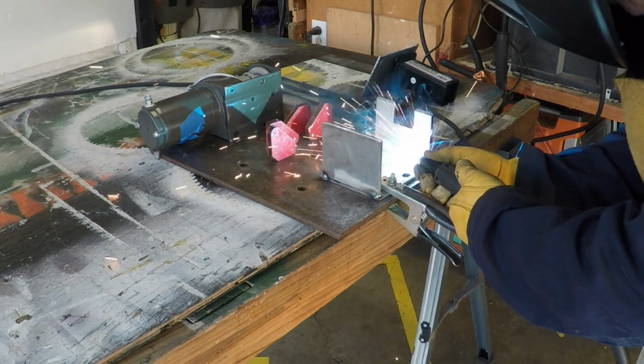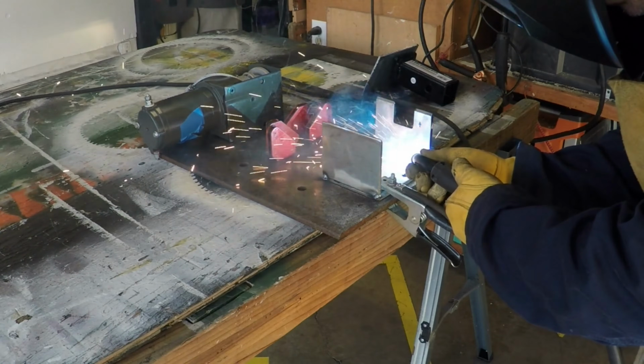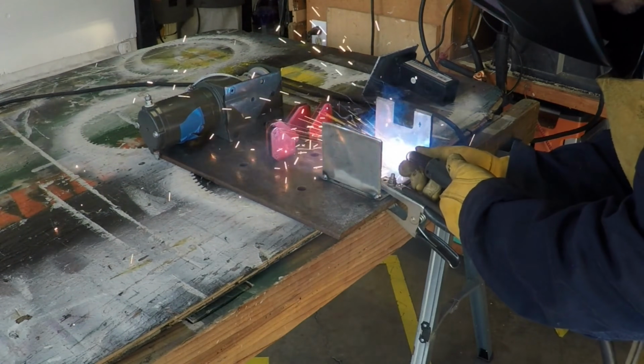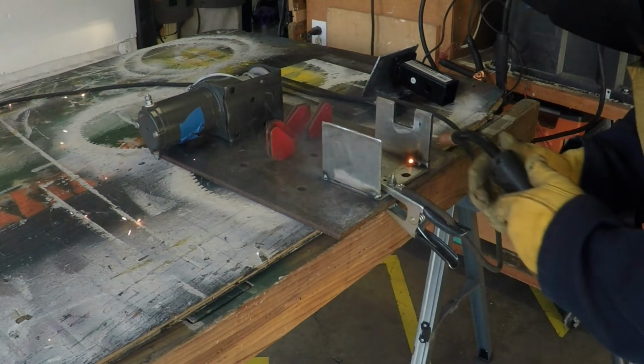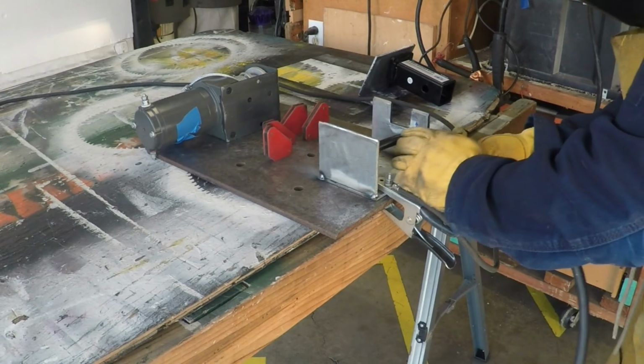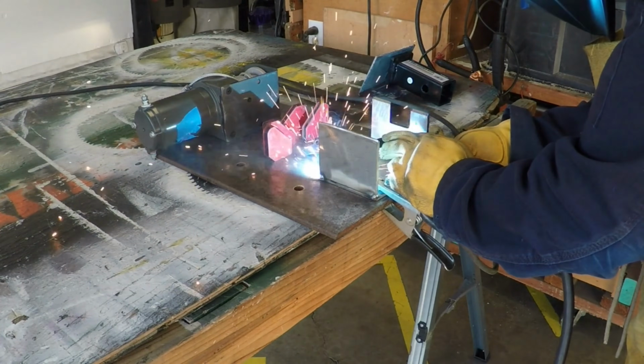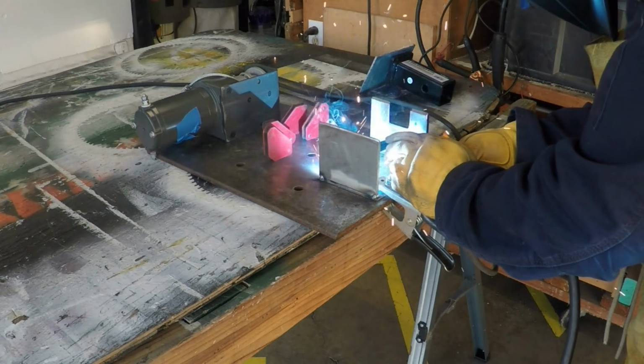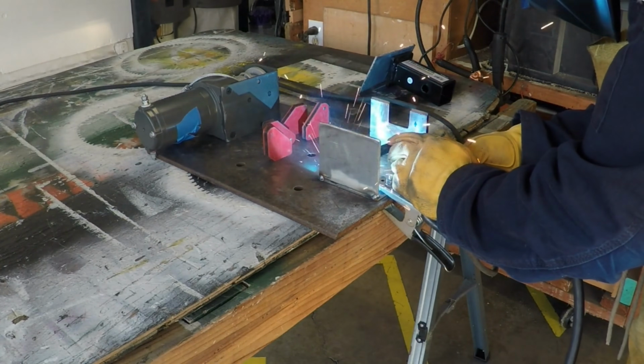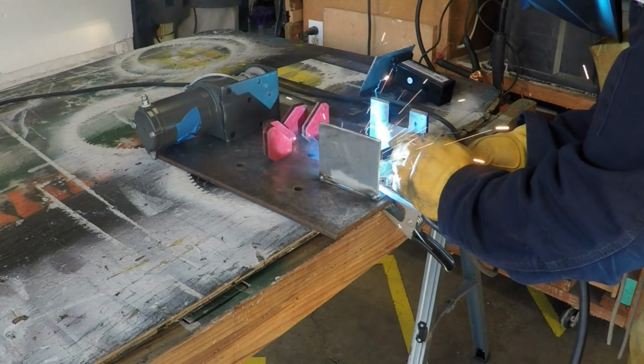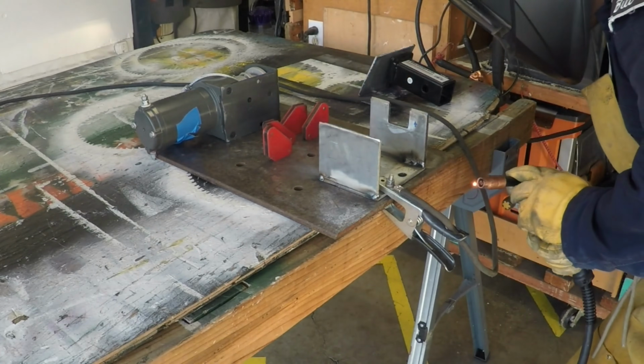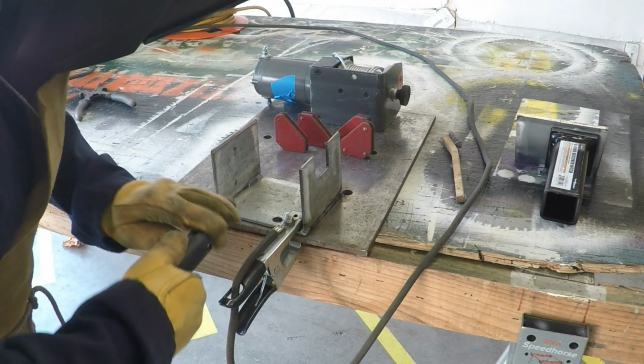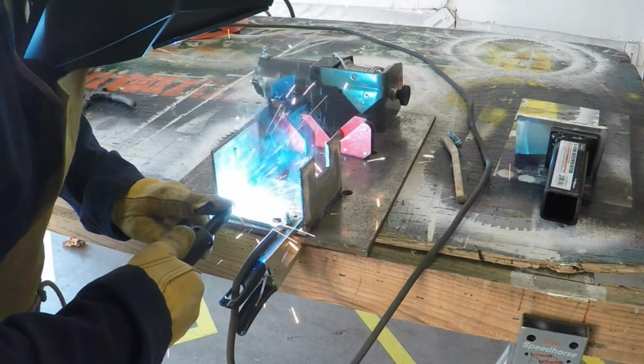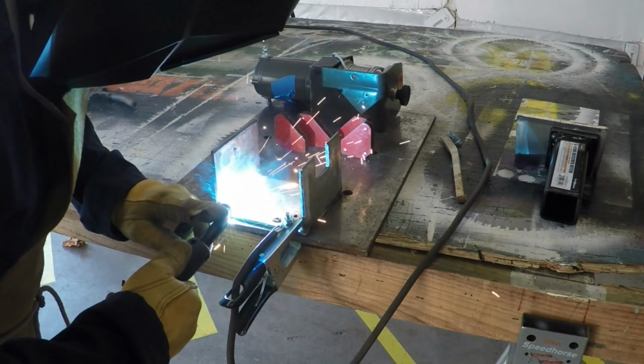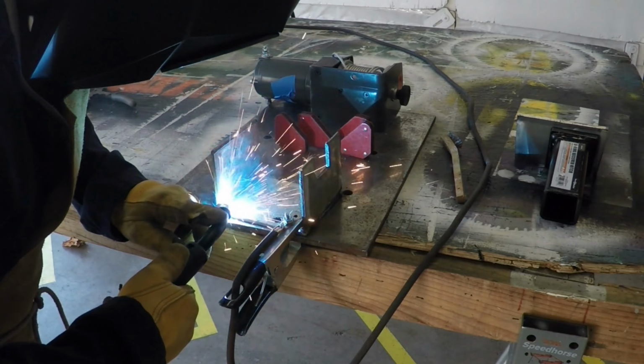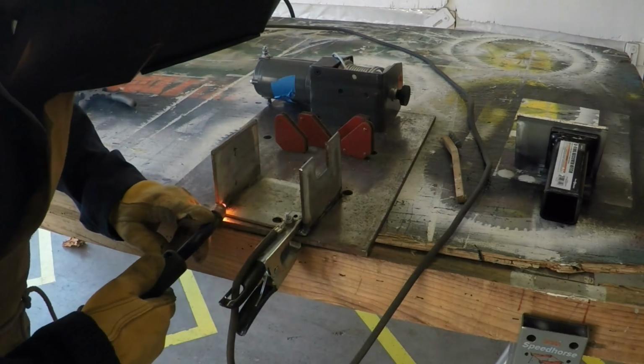Some welding techniques I use is I tack weld the part into place first, verify the metal's properly aligned, then go back and start adding my permanent weld. If you have too much heat build up in one spot, your metal will warp. So that's why I'm doing about an inch of weld seam, then moving to a new spot and welding there while the weld seam cools down a little bit. Notice all the smoke I'm producing is going off to the left. This is because I have a fan blowing across me to try to push all the smoke out through the garage door, and hopefully away from my face.